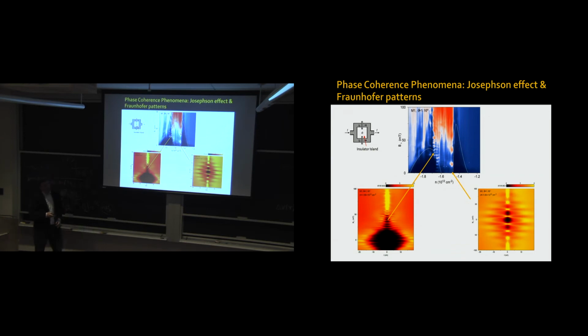Now, I just told you that the maximum critical temperature that we have is of the order of a Kelvin, 1.7 Kelvin. Now I'll show you data with a higher critical temperature. So we might wonder, how strong a superconductor is this twisted bilayer graphene? After all, these cuprates have TCs of 140, 160 Kelvin. So what's the big deal?